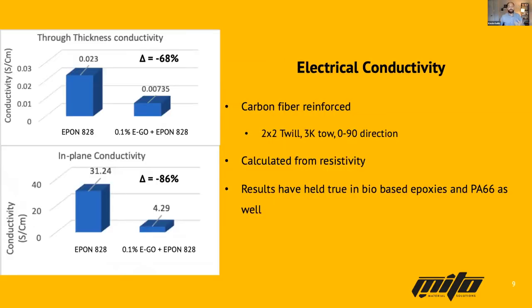Within that same EPON 828, we did some electrical conductivity testing with carbon fiber involved, and we saw that whether it's the volumetric or surface conductivity, it dropped anywhere between 68% and 86%. And that's held true across nylon 6/6, bio-based epoxies, polyester, you name it.